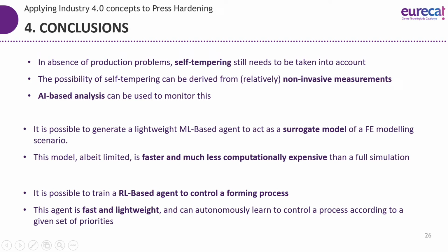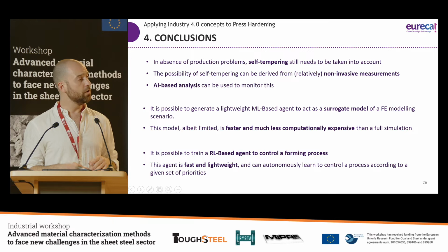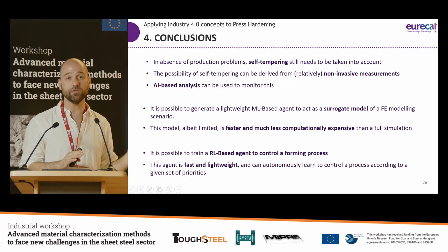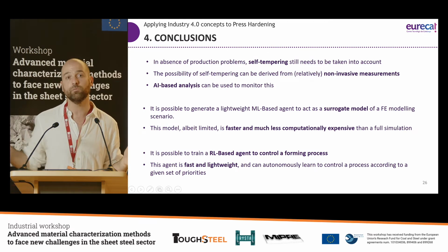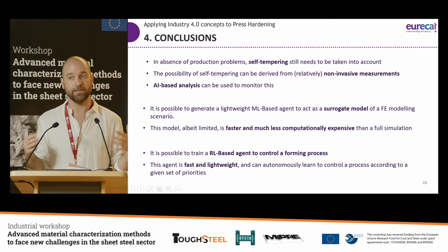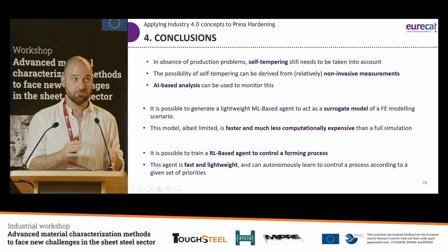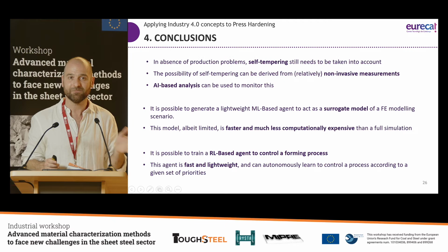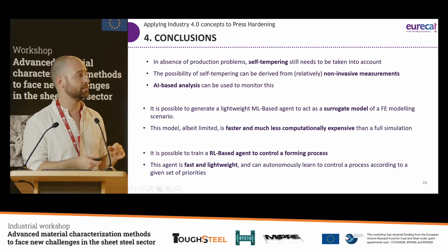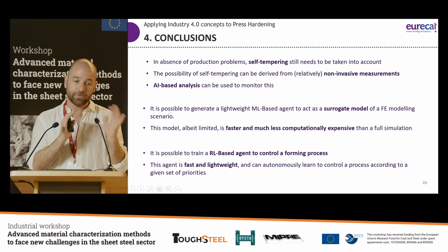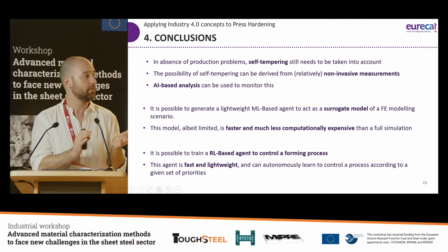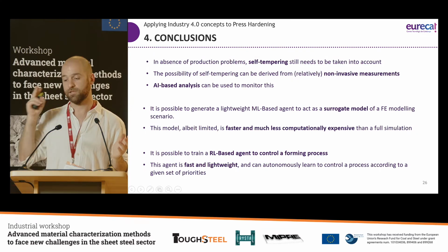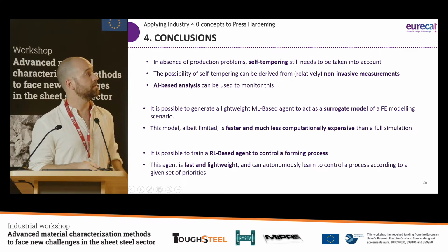In the absence of production problems, we said that self-tempering is an issue that appears, and it basically depends on which temperature the component ends the production cycle. We saw that we can make simulations, but we can also approximate these simulations via surrogate models. These surrogate models are simpler, they need to be trained, but once they are trained, they work almost as well as the simulation and much, much faster, a couple of orders of magnitude faster. And then we can also use this same kind of models and machine learning-based agents to control the system, to approximate the end result. And this is everything from my side.